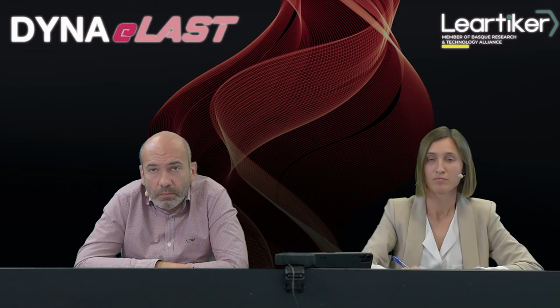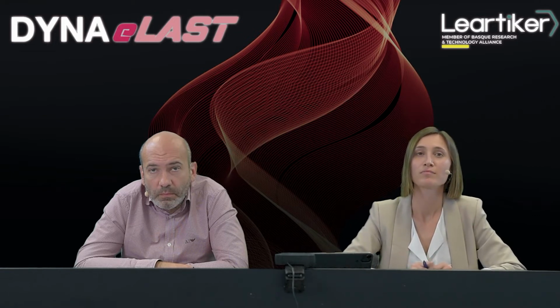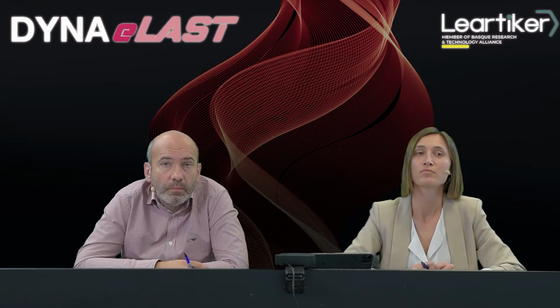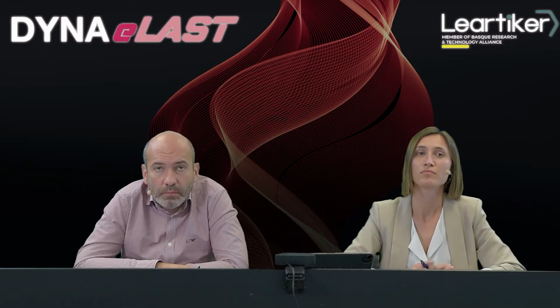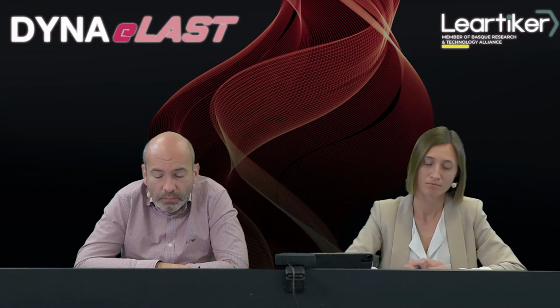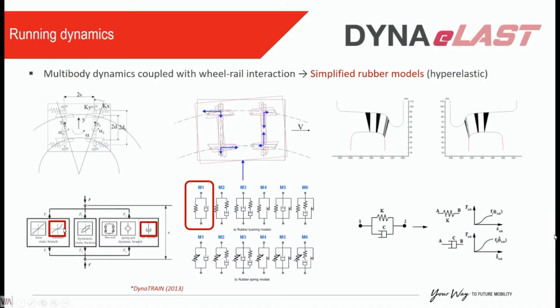But when it comes to actual multibody simulations, we really need to use simplified rubber models, like I said. So essentially, we use a hyperelastic model where we use a nonlinear force deformation curve, but that's about it. Usually, we also have a dashpot in parallel, but this is not even modeling the viscoelasticity in detail. It's usually just a constant value proportional to the critical damping, and that's about it. To be fair, when it comes to the objectives of our simulation, this is enough. There might be some scenarios in which we don't have the required accuracy, but in general, it is enough to comply with all the standards and to make sure that we have safe trains.